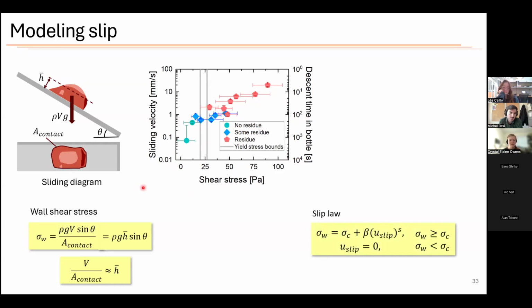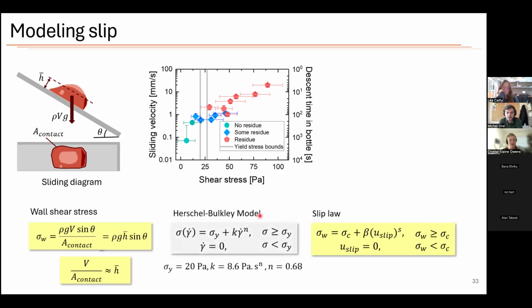We can understand this also using a slip law. The wall shear stress is equal to a critical stress plus a factor times the slip velocity to a power. You can see this is very similar in form to what we know as the Herschel-Bulkley model. This is a common slip law for yield stress fluids, and we find this fits well to our data, with parameters of a fairly low critical stress. This is actually the thing that something like LiquiGlide would fix. While we want to study the material itself, LiquiGlide would fix the slip properties of the vessel so that anything could slide with a much lower barrier. Maybe get rid of the critical stress entirely.